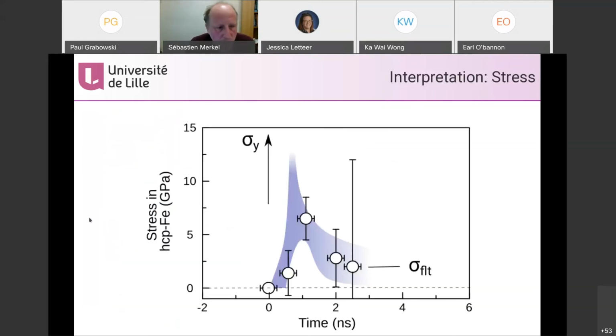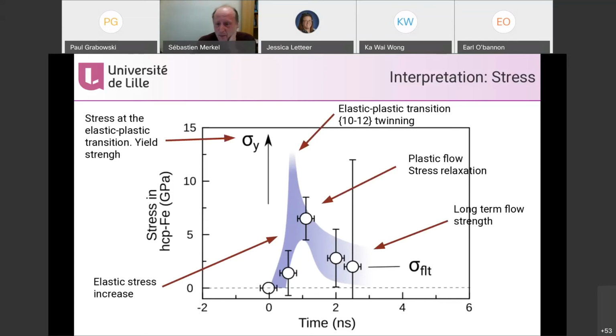Now, if I focus on the stress curve, so I've zoomed in on the stress curve which I showed you earlier. This is the time in nanoseconds, and the horizontal stress in HCP iron that we deduce from X-ray diffraction, and this is how it looks. And we were quite puzzled about that. That's not what I expected. And now this is how I interpret it. This is my interpretation. It's a bit busy, sorry.